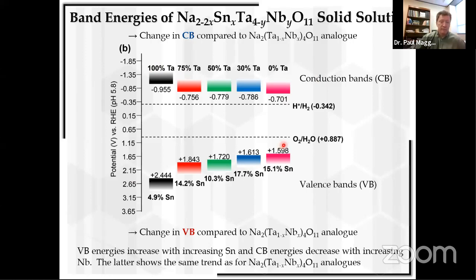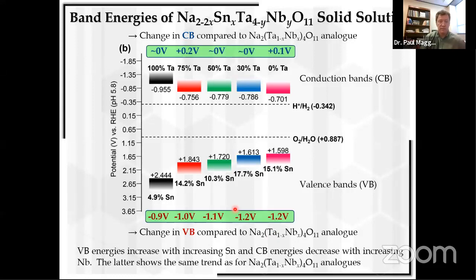And we can bring the bands together systematically, bracketing the redox couples for water oxidation and water reduction, which now shows the power of this technique to tune the band gap. And then in a solid solution, right, have a nice driving force for electron hole separation. And I'll skip through some of the details here just for reasons of time.